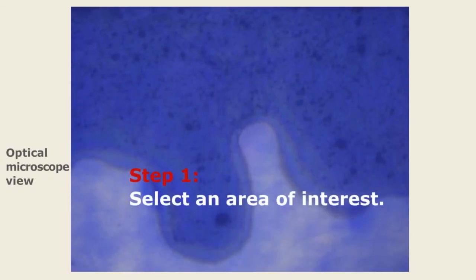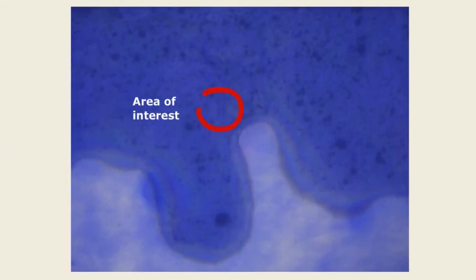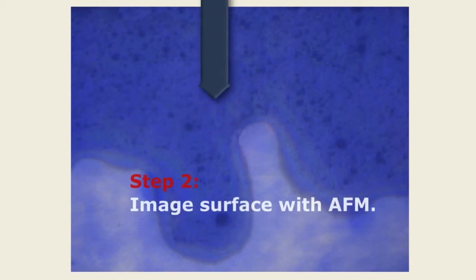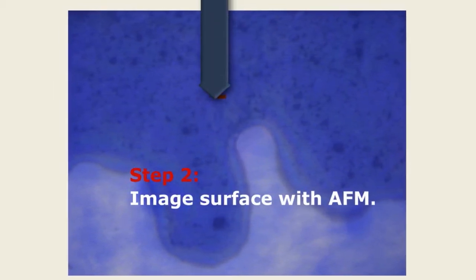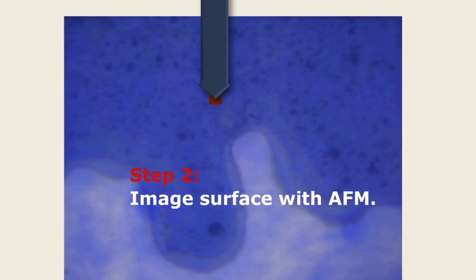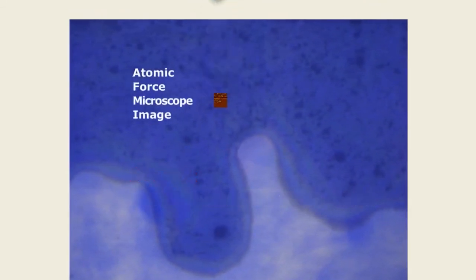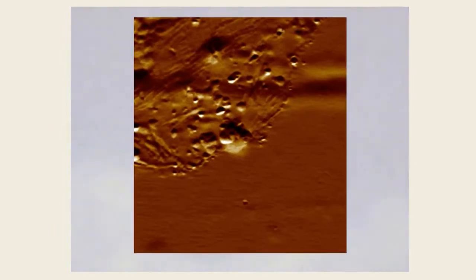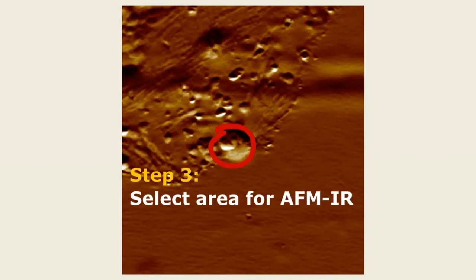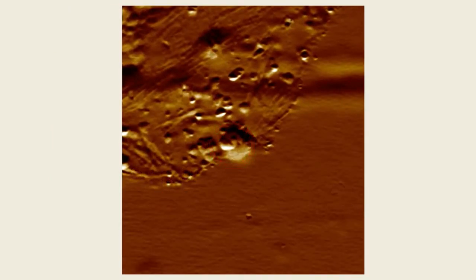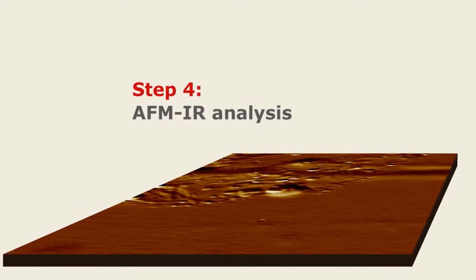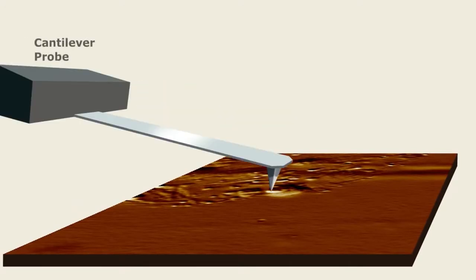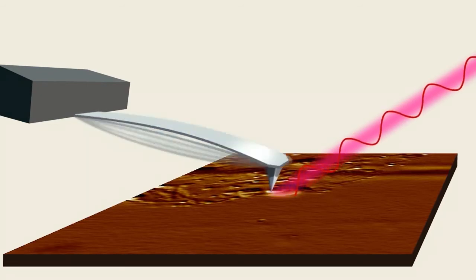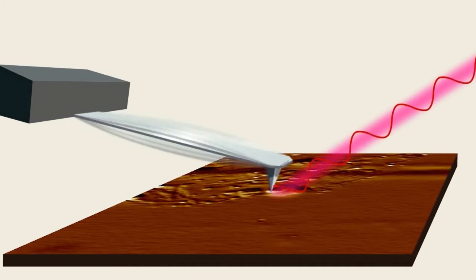We start out with an optical image, find a region that we want to scan. We scan it in a conventional way with the AFM tip, creating an AFM image. And then from the AFM image, we're going to pick a region where we want to do a spectroscopic measurement. So we're going to bring the tip down to the sample surface and start illuminating the sample with pulses of infrared light.